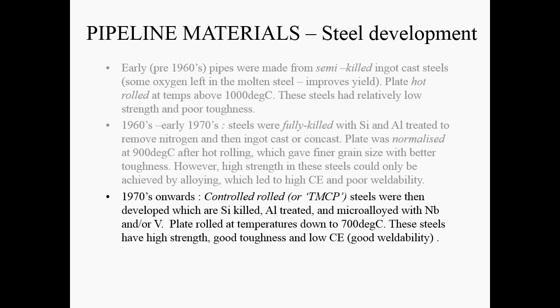So a silicon-killed, aluminium-treated and microalloyed steel, usually with niobium or vanadium, was rolled at temperatures down to 700 degrees C. And by rolling these steels, you can continuously refine the microstructure and make smaller and smaller grains. And these have very high strength and good toughness without having to add large proportions of alloying elements. So they have microalloying elements, less than 1%, but they don't have large amounts. And that means the carbon equivalent goes down, so the weldability is improved.